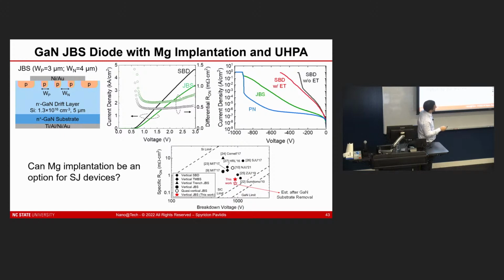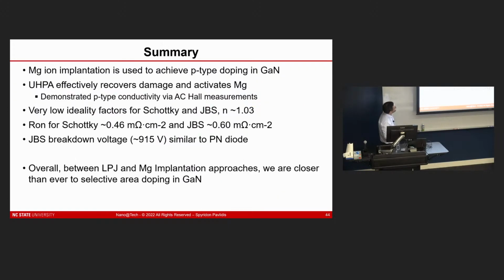If you look at what's been published in the past, we have now demonstrated for GaN devices record RON at 900 volts here. This little unfilled arrow is what we think is also maybe a path forward here. If you thin the substrate as well, you should be able to reduce those losses even further. But even with the thicker substrate that we have here, you put the whole thing together, we still have record RON and performance for these devices.